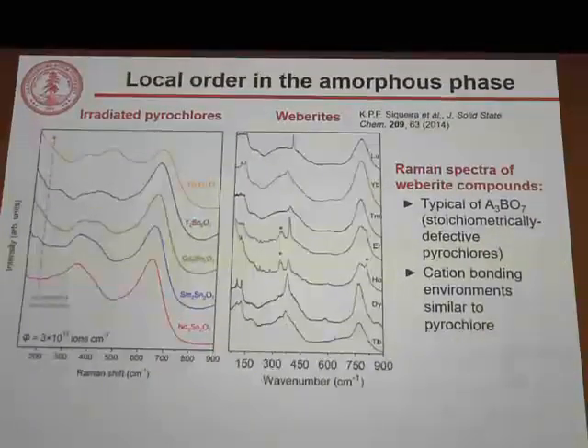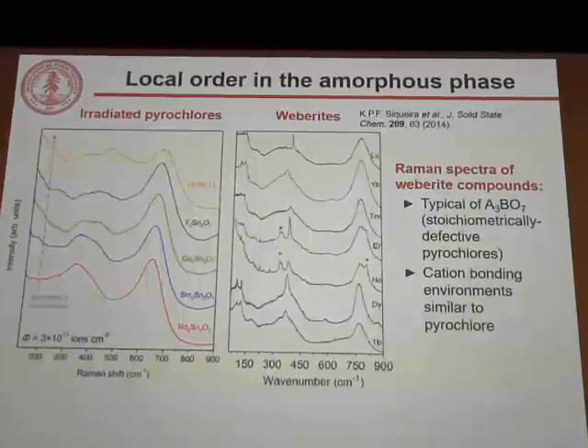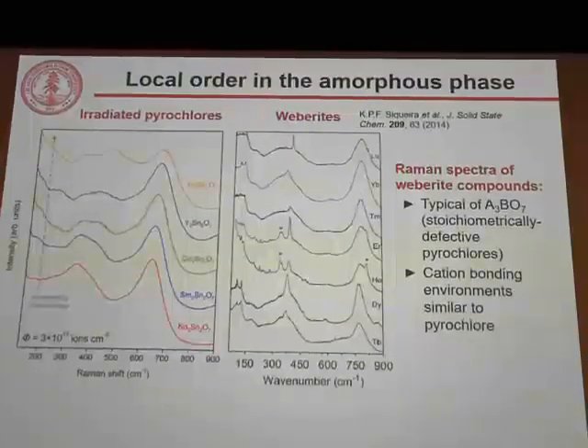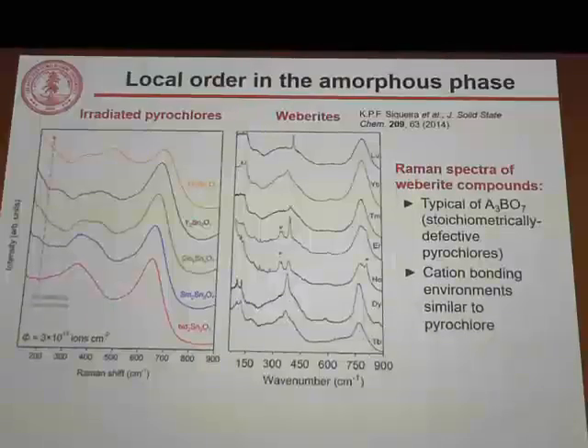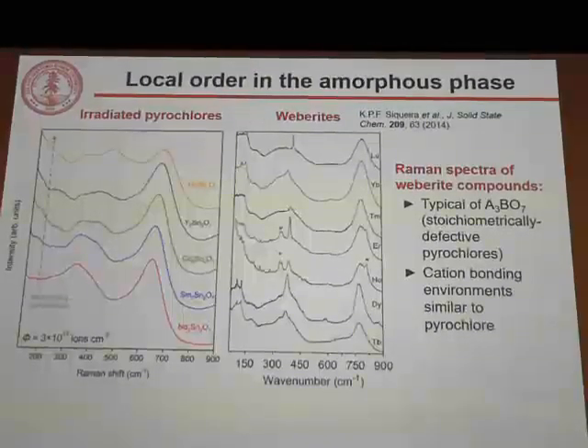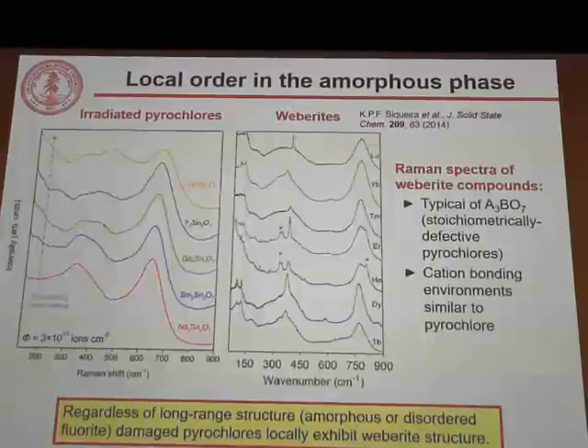If we compare the Raman spectra of all of these irradiated pyrochlores, which I mentioned are very similar, to those from the literature for Weberite structured crystalline compounds, we see that they match very well. These Weberite compounds are typically A3BO7 stoichiometry, so we can think of them as stoichiometrically defective pyrochlores. But they have cation bonding environments that are almost identical to the pyrochlores. So this research tells us that the disordered or amorphous pyrochlores all locally have Weberite type structures, and they will all, regardless of their long-range structures, have almost the same local bonding environments.